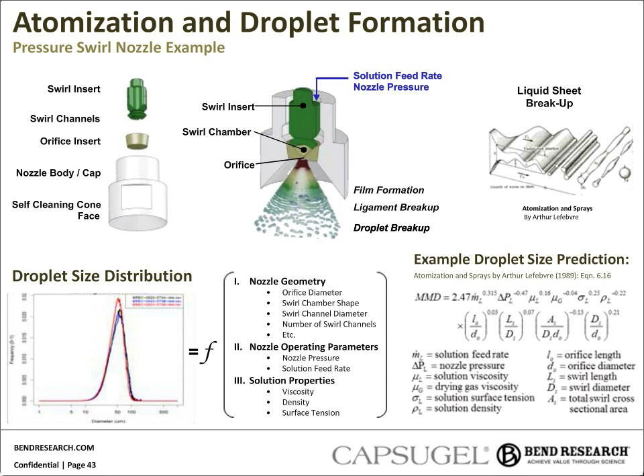The spray solution is fed at a high pressure through the swirl channels, which are designed to impart an angular momentum to the fluid, causing it to fan out as a liquid sheet on the inside of that orifice chamber, and then exit the orifice as a swirling liquid sheet or hollow cone. The liquid sheet thins out to ligaments and then breaks up into droplets.